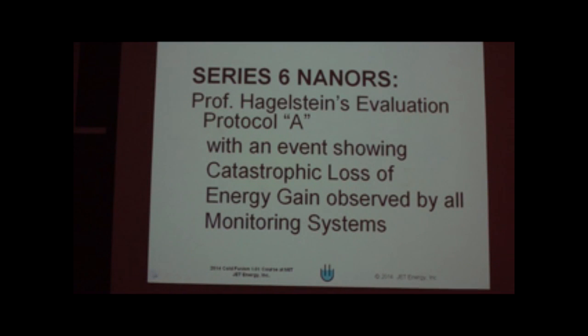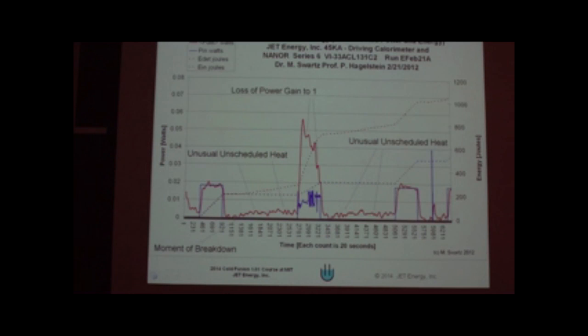Okay, things aren't always good in Mudville. It turns out that these materials can be destroyed. So this nanor actually had a burst of energy inside, and what happens is there's a little hole in the side that occurs, and the stuff squirts out. And here, when it's squirted out, it drops down to an ohmic control. We end up losing, for whatever reason, in that material, as a result of this catastrophic effect, the excess energy. It goes down to a gain of 1.